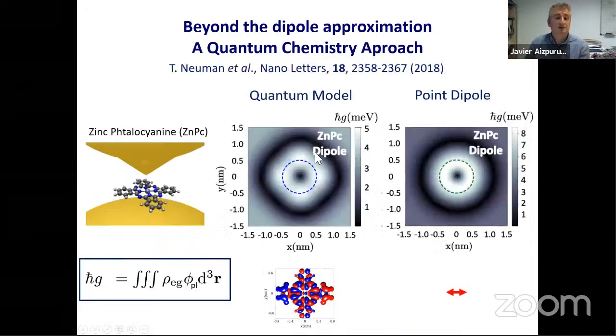So when one does this, we can map by moving this pico cavity, scanning the coupling strength, the coupling energy G as a function of position of this pico cavity, and get how the G of the full quantum model compared to the point dipole changes not only qualitatively, but quantitatively. You see that the full model gives a smaller coupling strength, a factor of 2, but more importantly, the full quantum model maps the four lobe. Maybe here it cannot be seen so clearly, but there is a four lobe here that in the point dipole is missed completely.